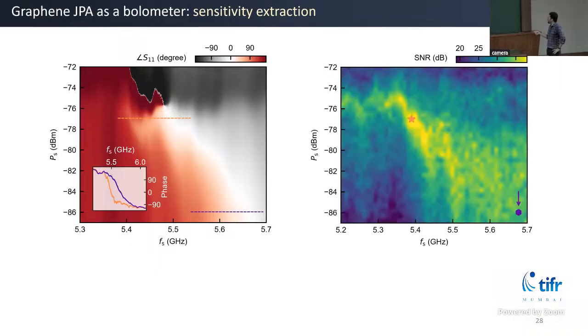And then we do some signal-to-noise ratio measurements. We track the sideband powers for a fixed heater power. Now we are sweeping this parameter space by changing the signal power and signal frequency. And right where the device becomes non-linear, we can see SNR contrast in the device. These yellow patches are high SNR points where you can park your bolometer and it will be maximally sensitive.